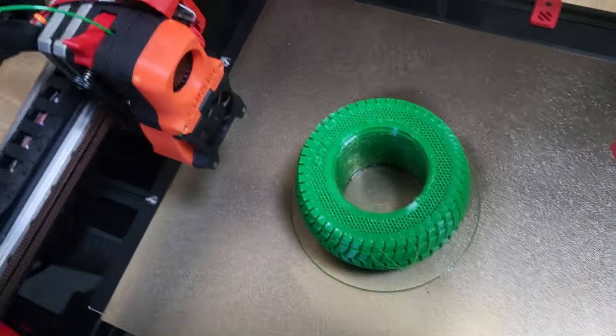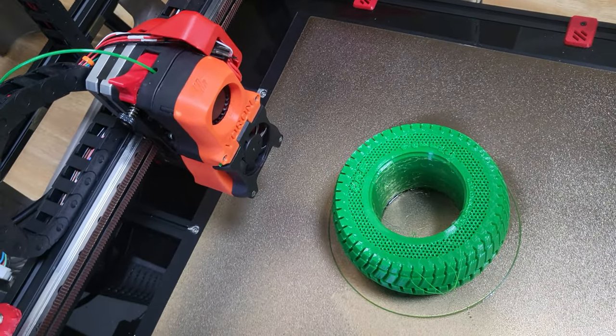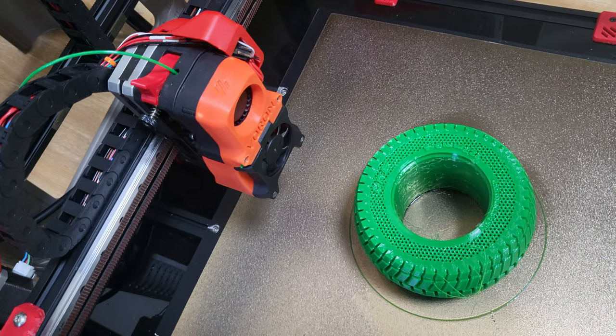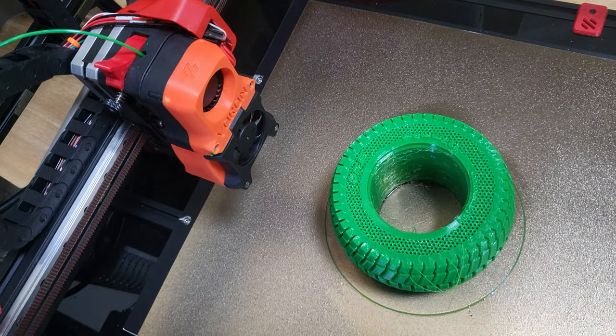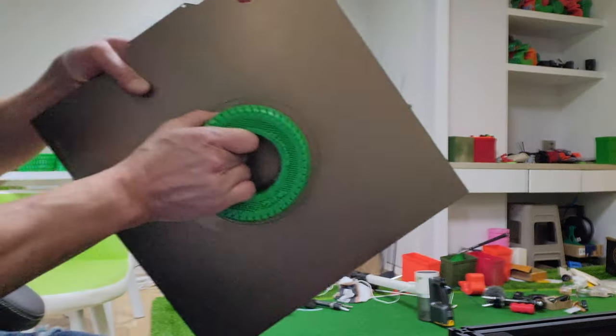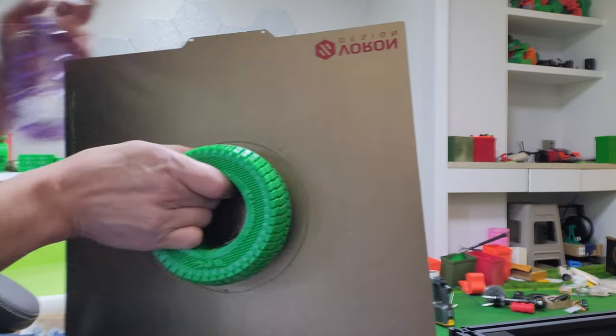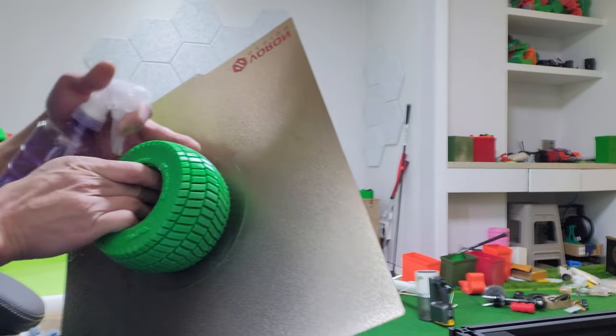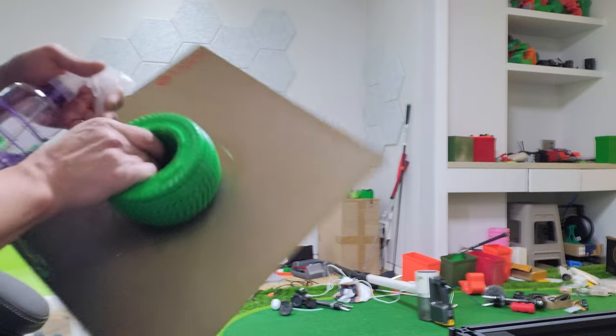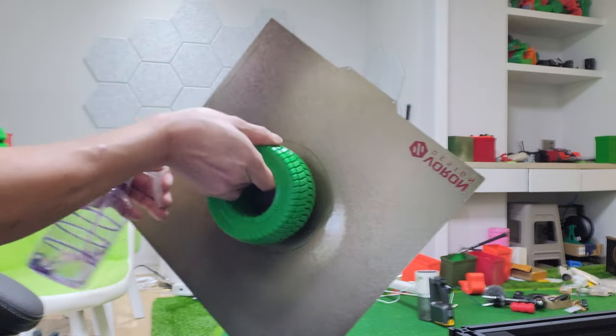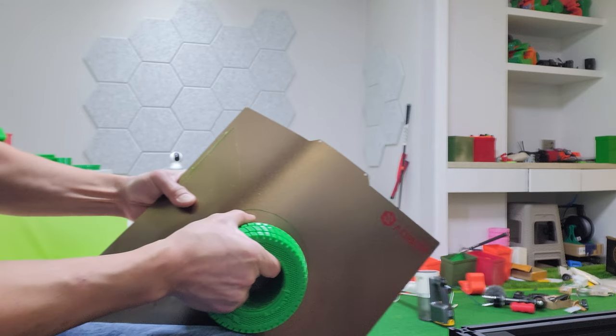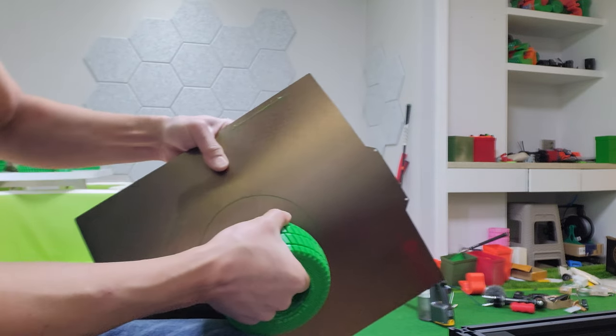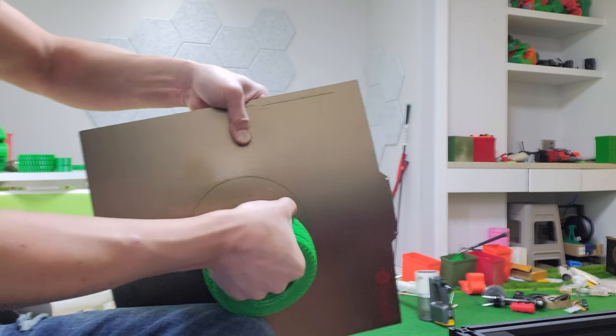I was able to print pretty good with TPU on my Voron with an afterburner and it got stuck there pretty well, so I have to heat it up. One of the things with TPU: if it gets stuck, don't force it. Heat it up to like 80 degrees and put some isopropyl alcohol on it, and it will come off much easier because you got a heated bed and then you got the alcohol to help you get it off.